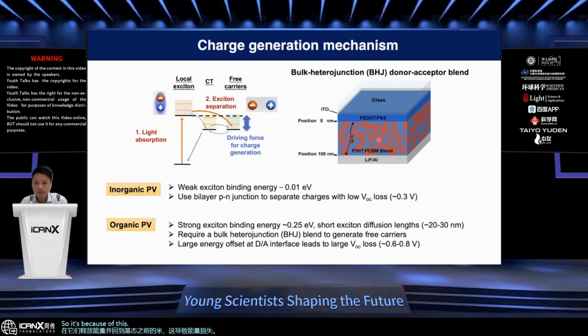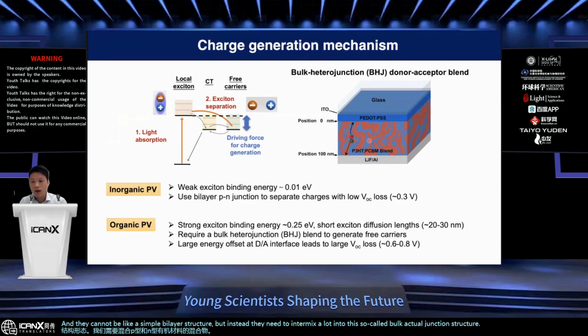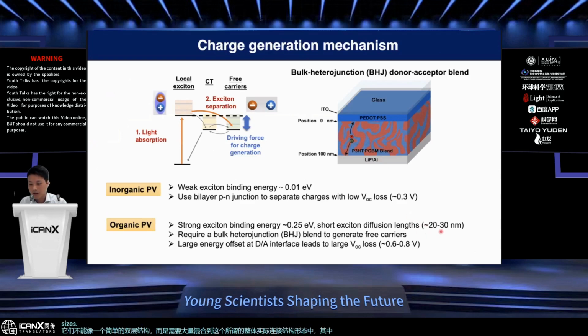So it's because of this condition that to make an organic solar cell, we need to rely on structural morphology. Okay, we need to blend in a mixture of p-type and n-type organic materials, and they cannot be a simple bilayer structure, but instead they need to intermix a lot into this so-called bulk heterojunction structural morphology, where the domain sizes are comparable to the exciton diffusion lengths. Okay, so that all the excitons generated, before they die away, can always diffuse towards an interface, 20, 30 nanometers within where they're born, so that they can reach this donor acceptor interface, right, and be able to separate into free charges.